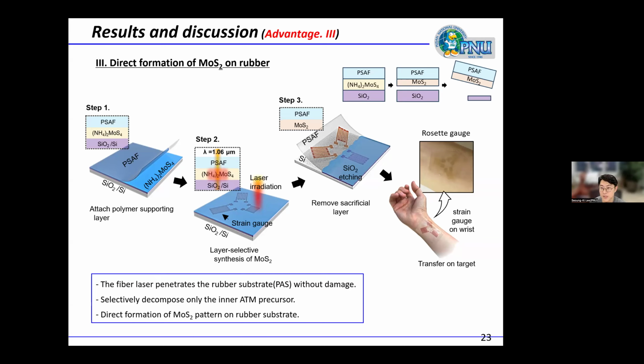Yeah, that is a really important question. Frankly, when we synthesize MoS2 using this method, we can simply synthesize it, but the weak point is that the grain size is really small. As you mentioned, it is weak to the oxidation process. So to maintain the electrical property, we should make a protective passivation layer on the MoS2 layer. In that case, we can avoid some toxicity issues when this sensor is attached to our skin. Yeah, thank you.